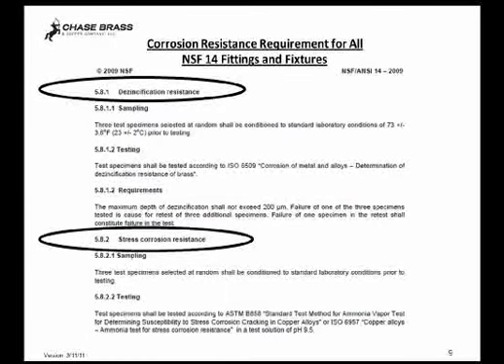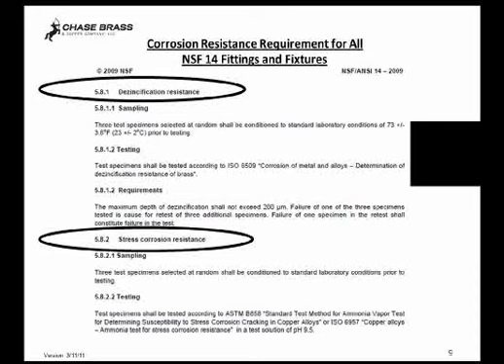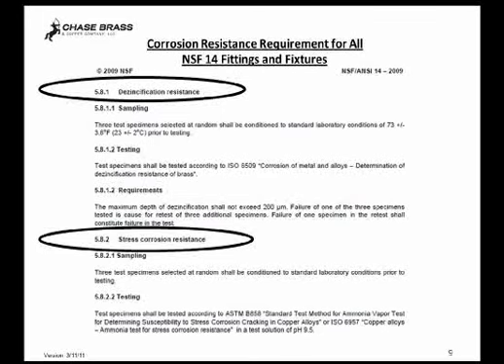But what that means is that in stress corrosion cracking, when you have a combination of stress, high levels of stress, and then an environment that attacks the grain boundaries of the material, and in this case, when we're talking about copper alloys, that's ammonia or amines, think Windex, it will cause the part to crack in a very short period of time, whereas in the absence of either one of those two factors, it won't crack. And the things that affect the amount of stress that a part's under is how the material is produced, how the parts are produced from that material, and then the installation of those parts.